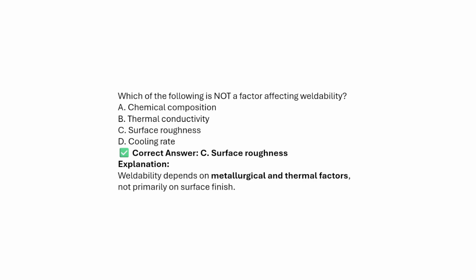Okay. Next, which of the following is not a factor affecting the weldability? First is A, chemical composition. Yes, because whatever elements are present in the alloy will affect the weldability. Next, thermal conductivity. Yes, if the thermal conductivity is high, then we have to provide more heat to the material, so that definitely affects the weldability. Next, surface roughness. No, because surface roughness doesn't affect it. Next, cooling rate. Yes, cooling rate also affects it, because a faster cooling rate may form martensitic phase or highly deformed grains. If it is a slower cooling rate, it may form more equiaxed grains. So the answer will be C, surface roughness. Weldability depends on the metallurgical and thermal factors, not primarily on the surface finish.